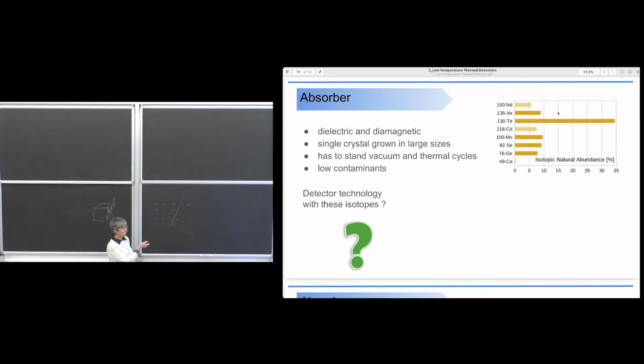However, I remind you that, at least I think that yesterday I told you, maybe I didn't, that there are two drawbacks in the use of cadmium. One is that it has a high cross-section for neutrons, and therefore is a potential background. And the other is that not this isotope, but the isotope 113 is radioactive. So it is true that once you enrich the cadmium, you will remove most of it, but it's not nice.